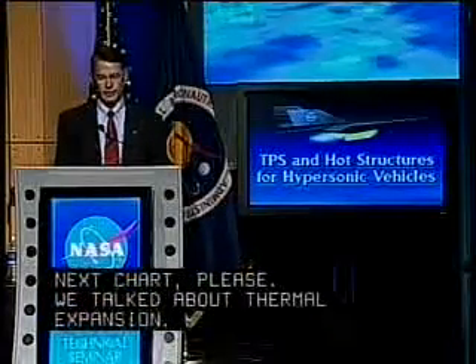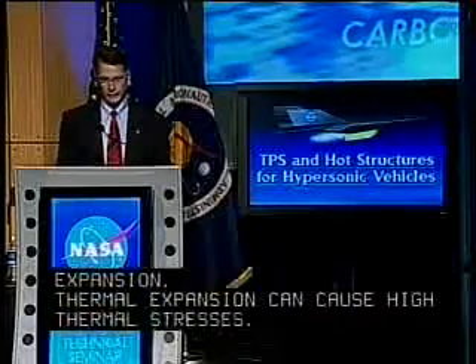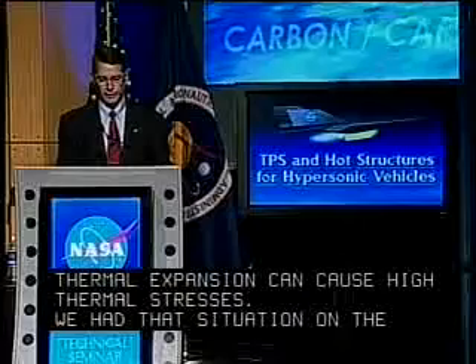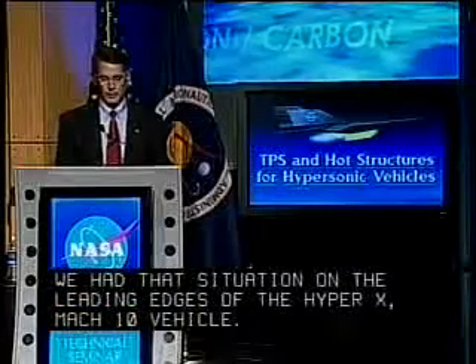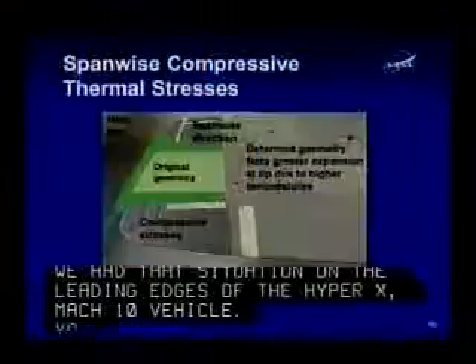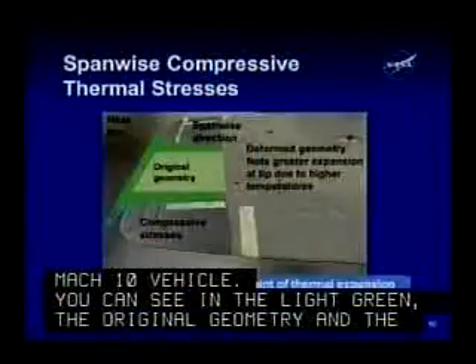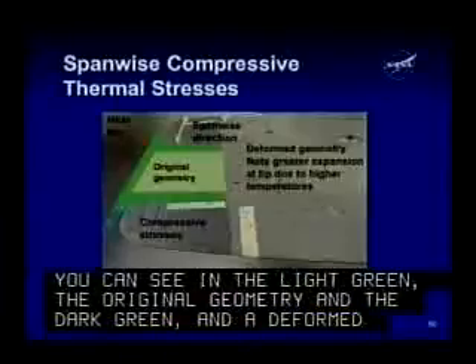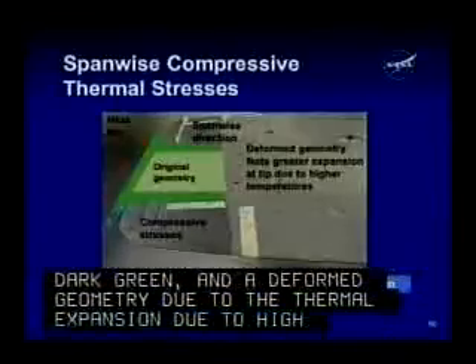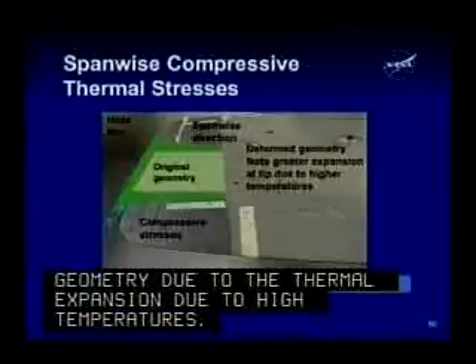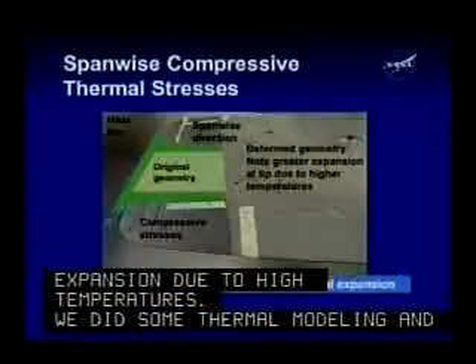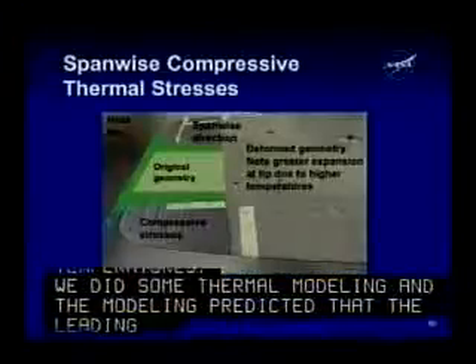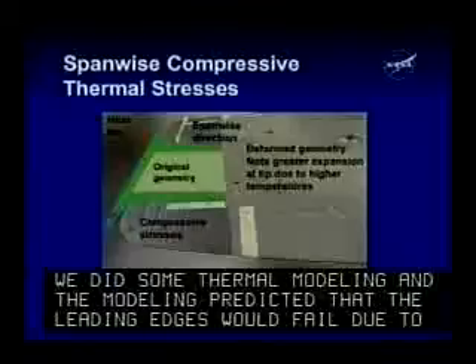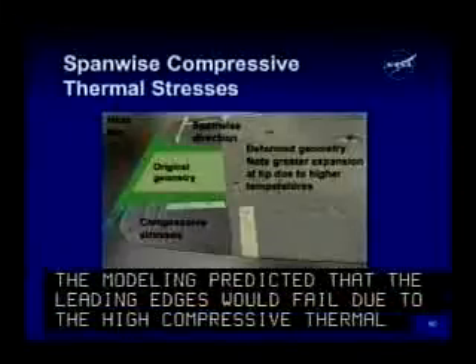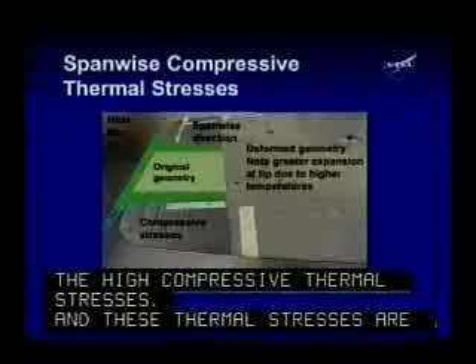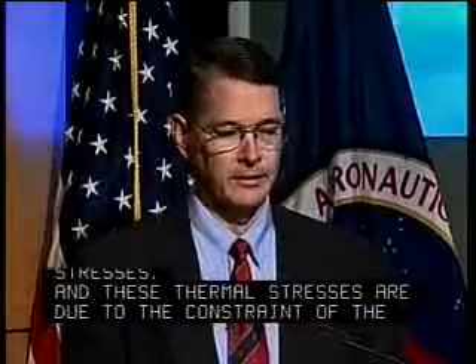Okay, we talked about thermal expansion. Thermal expansion can cause high thermal stresses. We had that situation on the leading edges of the HyperX Mach 10 vehicle. You can see in the light green the original geometry and in the dark green a deformed geometry due to the thermal expansion at high temperatures. We did some thermal modeling, and the modeling predicted that the leading edges would fail due to the high compressive thermal stresses. And these thermal stresses are due to the constraint of the thermal expansion as it gets hot. Next chart, please.